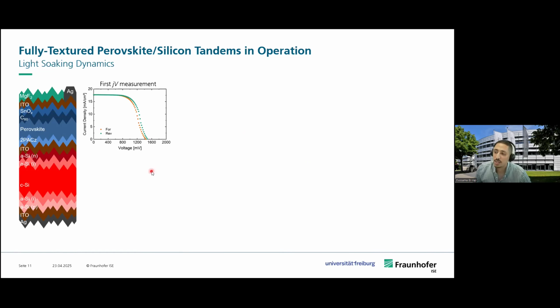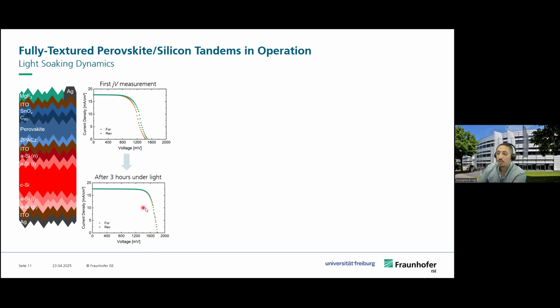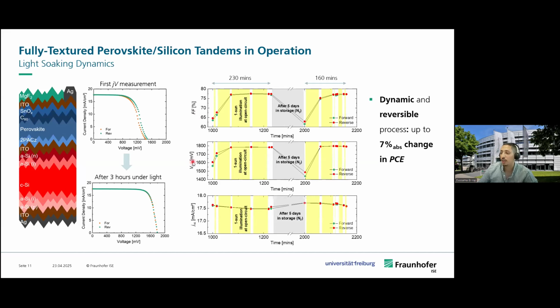What was interesting to observe is that once we kept the cell under illumination for a period of around 3 hours, the hysteresis was completely resolved, and we had a much improved fill factor and VOC. To see this a bit better, here you can see the fill factor, the VOC, and the JSC over time. When we keep the cell under light illumination, you see the fill factor taken from a reverse JV scan and a forward JV scan, and in between the cell is kept at 1 sun illumination under open circuit conditions. You can see that we can gain more than 10% absolute in fill factor, and then there is a stabilization. And in terms of VOC, we can gain up to 300 millivolts, which is really enormous.